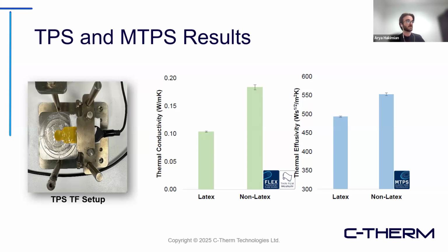But from a results perspective, we can see that comparing the latex and the non-latex versions, there was a notable difference in both the thermal conductivity measurement tested on TPS and a very similar trend observed in the effusivity from the MTPS. So again, kind of showing that the non-latex version actually was higher in thermal conductivity than the latex counterpart.